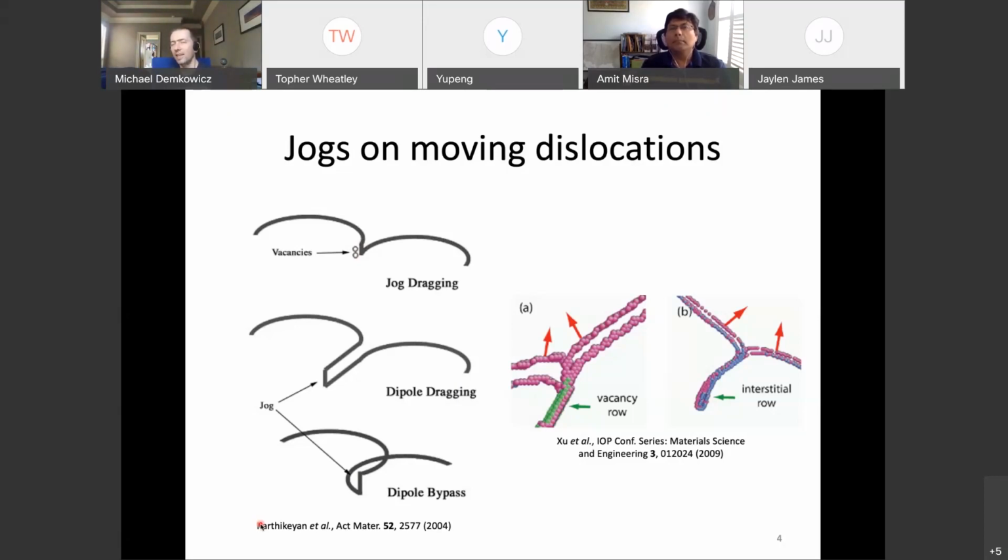No. That expression was developed only to describe how the activation energy for thermal activation of a double kink pair varies with the applied stress. The intention there was not to imply that there is an activation energy beyond the mechanical threshold. So beyond the mechanical threshold, there's no more activation energy. Okay, right. Okay, thank you.